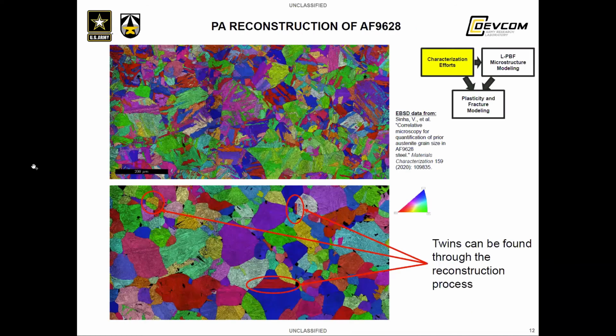So now moving on to actual reconstructions of AF9628. I'll present results for a few different samples of this material. To start, this EBSD data set for the cast AF9628 sample shown on the top is the complete data set from some of the images shown earlier. Below it, the reconstructed parent austenite grains are shown. The algorithm used to perform the reconstruction automatically uses a cluster growth type algorithm to find viable groupings of martensite grains.